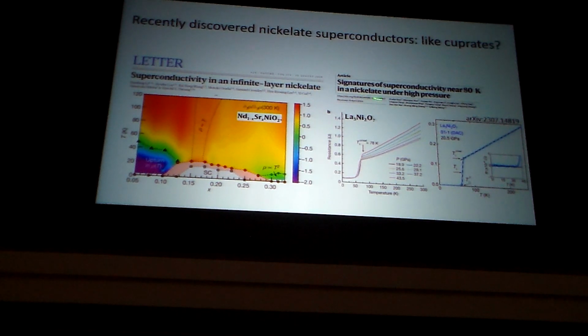And very recently, under high pressure, someone has taken this compound, put it under pressure, and found 80-degree superconductivity. Now that's pretty high. That's really getting up there near the cuprates. And there's also a linear in T resistivity above the superconducting transition temperature. So this is one of the new hot areas where people are trying to look and trying to understand this. Okay, but unfortunately, this word high pressure is not good. You can put pressure on materials, we do it in our lab, but it makes all the experiments much more difficult. Nevertheless, this is an interesting recent development.